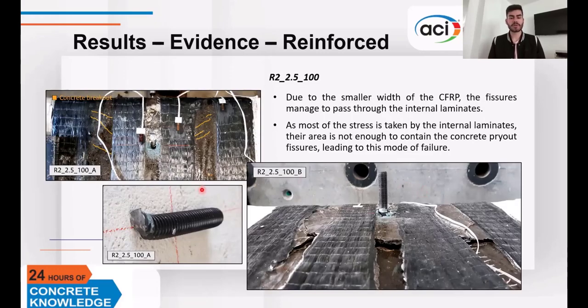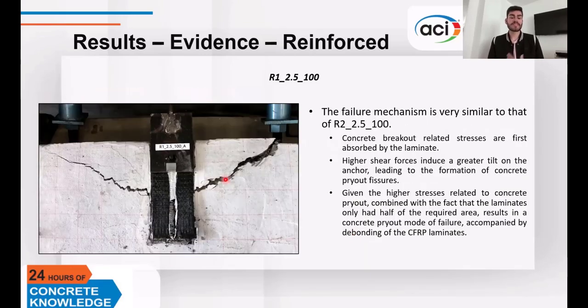This is total area distributed in two laminates on each side. You can see that as the laminate width is smaller, concrete breakout cracks propagated beyond the innermost laminates. This ineffective crack control is what led to the formation of a concrete pry-out body, which caused the debonding of the FRP. This is a specimen with half of the total reinforcement. We have concrete pry-out here as well. You can notice that cracks originate at the back of the anchor.